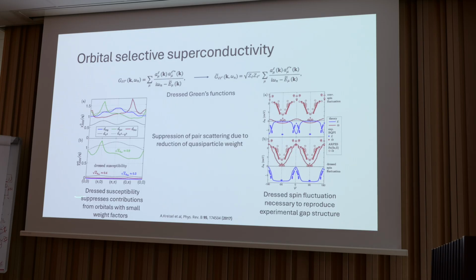And so this is one paper where they try to account for this orbital selective superconductivity by dressing these Green's functions with the quasi-particle spectral weight included. So the top is the susceptibility without dressing, and the bottom is the dressed susceptibility. This is specifically for an iron selenide model, I think, and take it with a grain of salt because I think there's some question about the gap structure that they determined for that paper. But the idea is there that